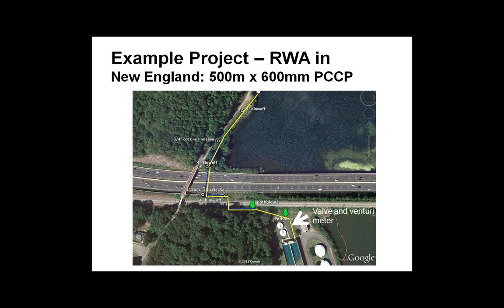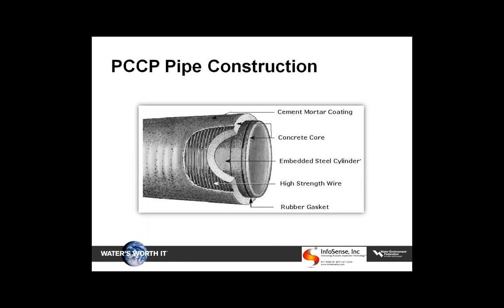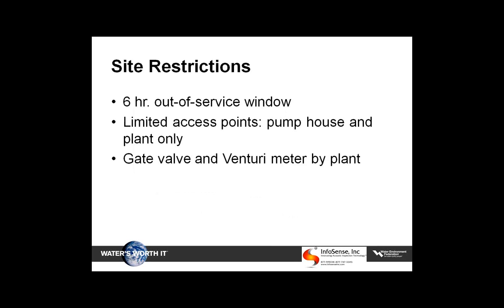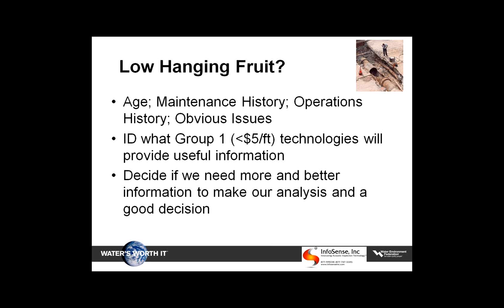I'd like to end up with a very nice little example case study. This is in New England, where there was a utility with 500 meters of 600 millimeter pre-stressed cylinder pipe on a water intake, going from a water intake system underneath the interstate and along an interstate right-of-way, which made it a very critical line into a water treatment plant. It was all pre-stressed cylinder pipe, with some fairly hefty site restrictions. We could only have the system out of service for a 6-hour window, and that was all we had. Very limited access points at the pump house and the plant, and we also had gate valves and venturi meters that we had to get through.